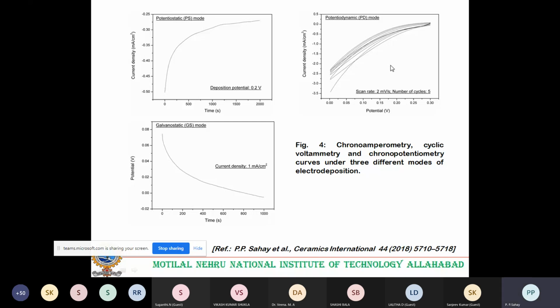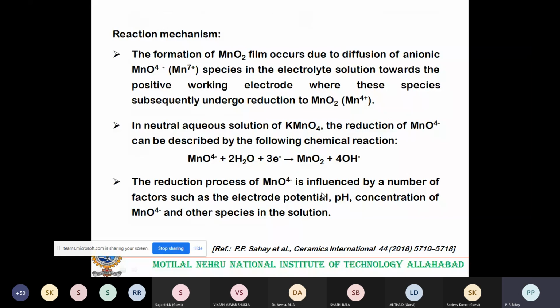And in the case of the galvanostatic mode, here the current is constant. I told you that there are three different modes. When the current is constant, we are measuring the potential and time. When the potential is constant, we are measuring the current and time. So here also you see the potential first reduces rapidly, and afterwards gradually decreases. This is attributed to the interaction of the ions moving in the cathodic direction with the ions moving in the anodic direction, only because of this one and this one. So this is the deposition curve.